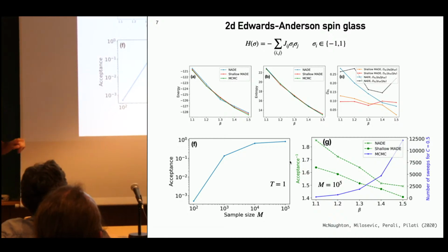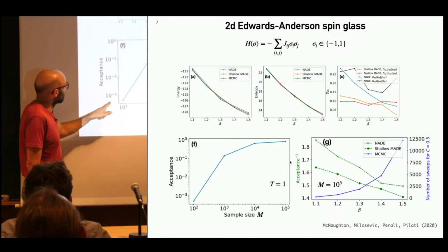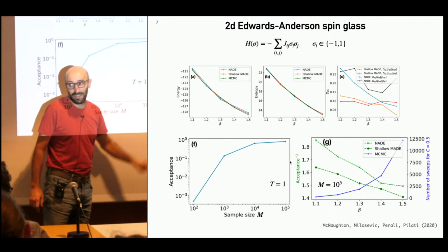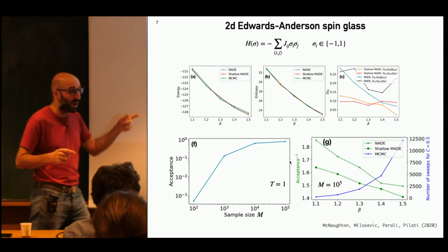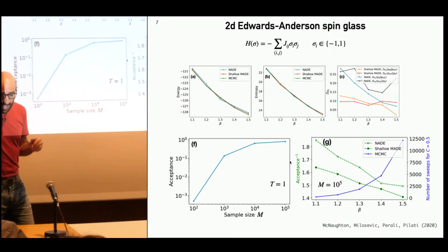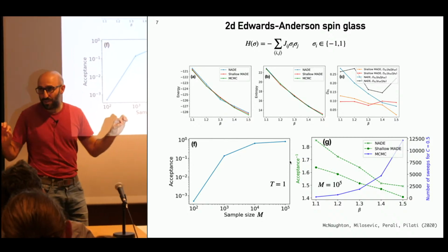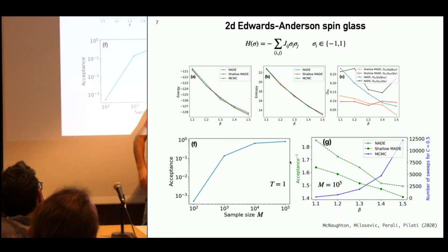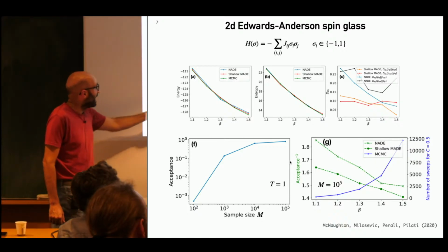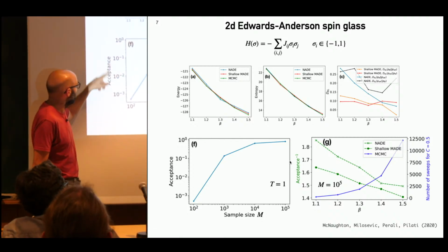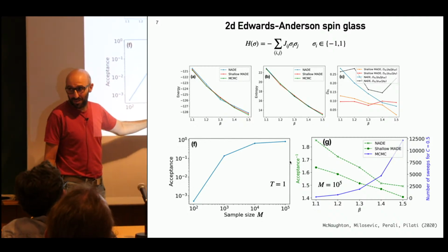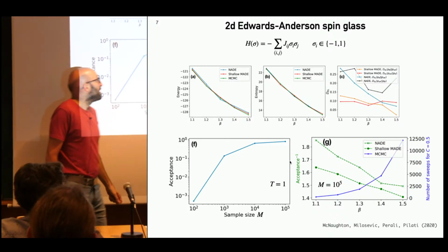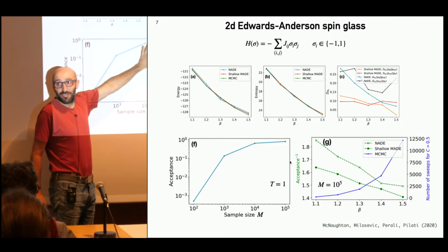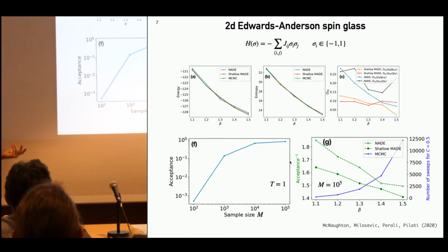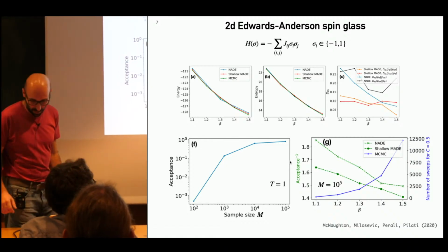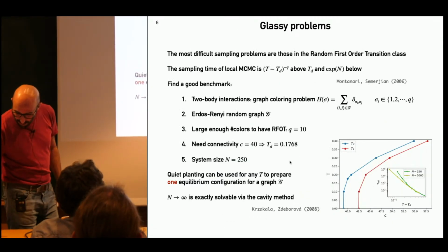One important thing for the next part is that in order for this to work, here we have 10 to the 5 training samples. We start at temperature 1 with 10 to the 5 samples generated from local MCMC. And then when we do the simulated tempering, each of these 10 to the 5 samples is evolved. So we always have 10 to the 5 equilibrium samples to train the auxiliary model. And actually, this is needed. This is the dependence of the acceptance rate on the training sample size at temperature 1, and you see that you need 10 to the 4, 10 to the 5 samples. If you reduce the training sample too much, then you have a very low acceptance rate, and things don't work well. Okay, now we said, well, this is promising.